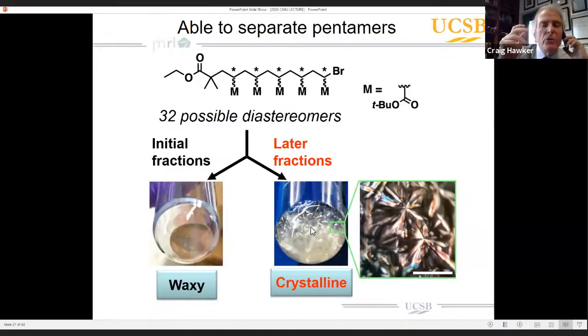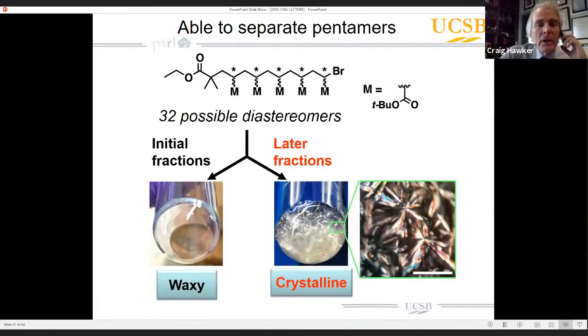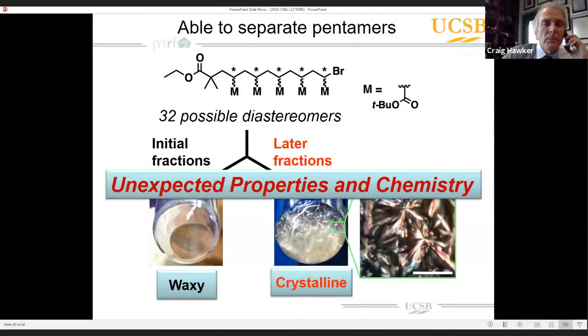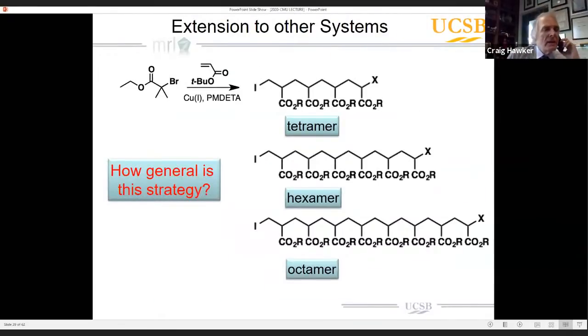So what I think that we're doing here, and we're still looking at this, is that we're starting to actually separate the pentamer according to all of the possible diastereomers. And obviously, the materials that are eluting later in the separation are just a little bit more crystalline because of their tacticity than those early in the separation. So these were some unexpected properties in chemistry that we started to observe for these materials that we were able to separate by Biotage.